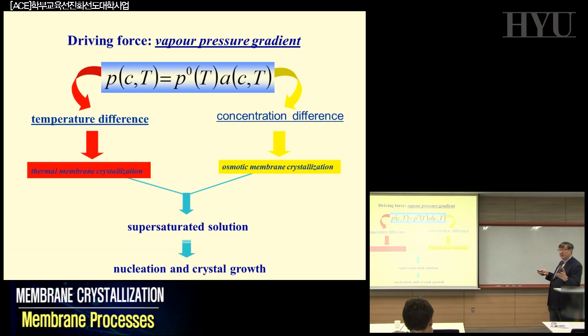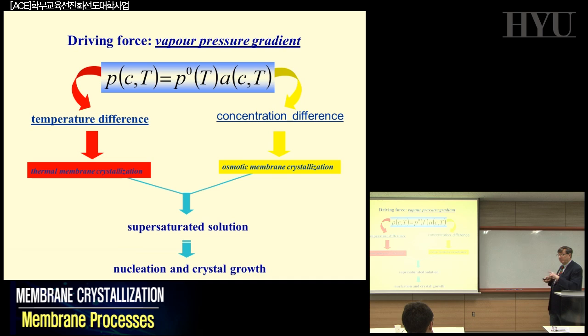Basically, the driving force in membrane crystallization, exactly as we discussed in membrane distillation, can be just a difference in vapor pressure across our membranes. It can be a temperature difference. Consider that we can also have a concentration difference. As we had membrane distillation and osmotic distillation, something similar to pressure retarded osmosis, we can also have a concentration difference here, and we have osmotic membrane crystallization if we're working with a crystallizer, or you can have thermal membrane crystallization if you have just a delta T across your membrane. And that is basically to create the supersaturated solution.